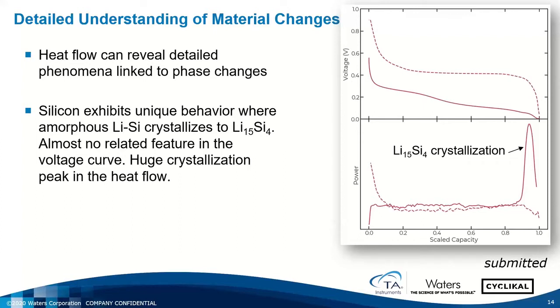Another thing that we can look at is phase changes. We can get really interesting heat signatures from phase changes. For example, here in silicon, a really interesting behavior is that silicon is amorphous on lithiation. Along here we have amorphous lithium silicon, and we know from X-ray diffraction that right here there's this tiny little feature that's barely noticeable. You probably wouldn't notice it in the voltage curve if you weren't looking for it. That happens when lithium silicon crystallizes to Li15Si4. But if you look at the power, although it's fairly constant here, there's this huge peak that shows up because of the crystallization.